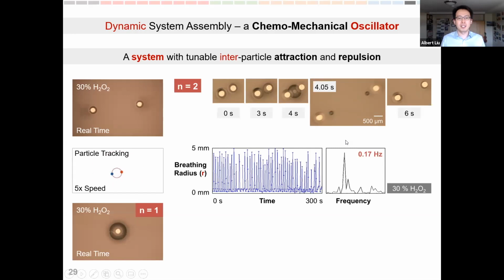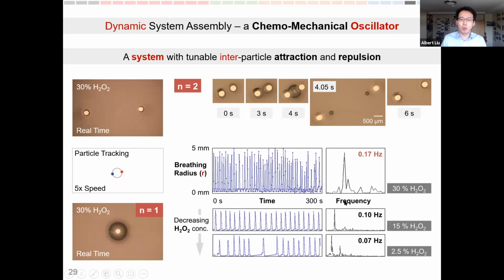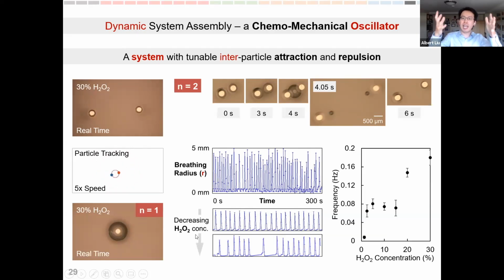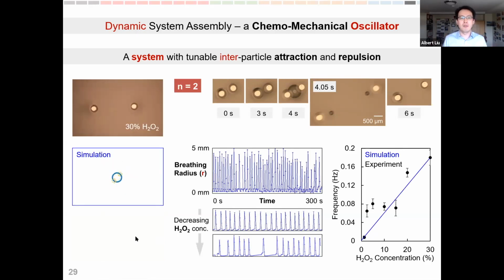So this is quite surprising, because there's nothing in our system that has prescribed a beating or an oscillation that has a given frequency. But indeed, if you track the particle trajectory and map out what we define as the breathing radius, which is basically another way of saying the distance between these two particles as a function of time, you can see that this oscillation happens at a very defined frequency. And this frequency can be further controlled by the concentration of the chemical fuel within the system, in this case, hydrogen peroxide. Because as the hydrogen peroxide gets more and more dilute, the oxygen generation rate is slower and slower. You can see that as we decrease hydrogen peroxide, we lower the frequency of such oscillation. And we can understand what is going on analytically using a very deterministic simulation model we have created, which qualitatively and quantitatively agrees with our experimental measurements.